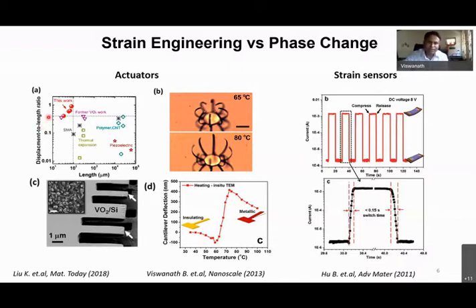And this is also compared with other materials, the displacement to length ratio, for example, for a cantilever. Among the many other cantilever materials like piezoelectric, bimetallic strips based on thermal expansion, or shape memory alloys, and so on, vanadium dioxide seems to show a very good displacement to length ratio. Even when you have short cantilevers, it can show very good actuation or tip displacement. So in some of these applications, as a result of phase transformation, there is a volume change. The associated stress can be used for actuation purposes. That is what is shown here as a cantilever, the cantilever deflection, and how it can be reversibly tuned.